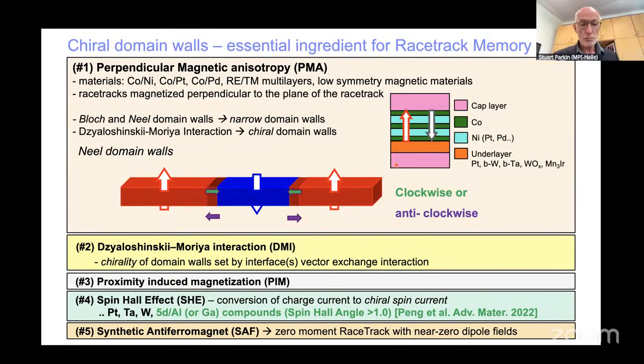This interaction leads to the moments pointing in a chiral direction. So let's say if we go to this racetrack where you have a red moment pointing up and the blue moment pointing down, this interface Dzyaloshinskii-Moriya interaction stabilizes a domain wall which is Néel-like. The magnetization will rotate from up to down in the plane perpendicular to the wall. This is a Néel wall. At the same time, it will rotate in a clockwise direction, let's say for platinum, but anti-clockwise for tungsten.